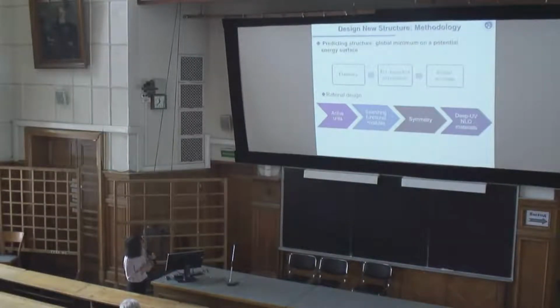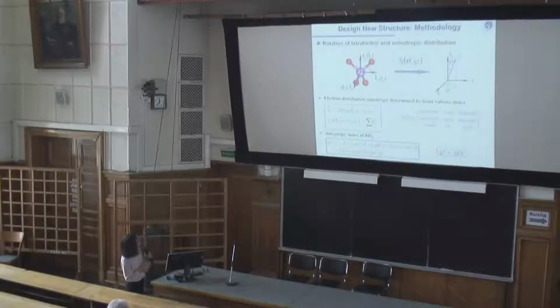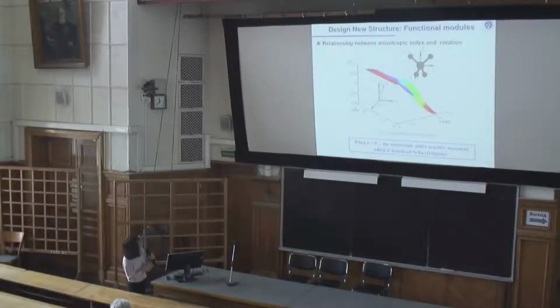Here we want to ask, can we start from the active units and the functional modules, break the symmetry, and design new structures? So firstly, we go back to the tetrahedron. Because we know that this key factor is very important for the birefringence, we try to identify this key factor, and we make a rotation for this. And we can see from this picture that if the key factor is very high, the birefringence is higher. So we can say what kind of tetrahedra should have a large SHG response.